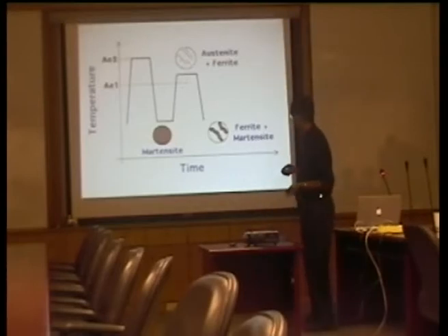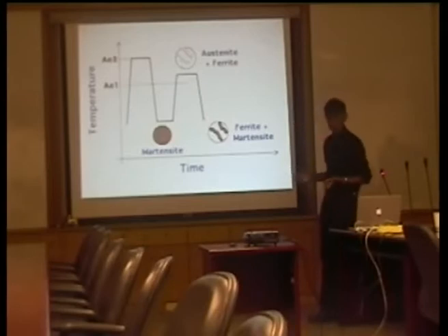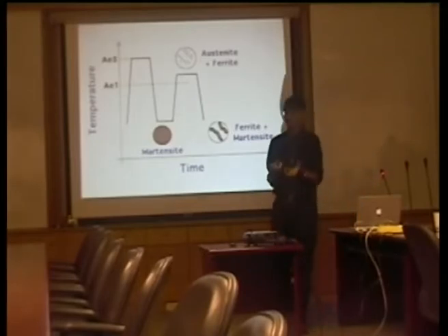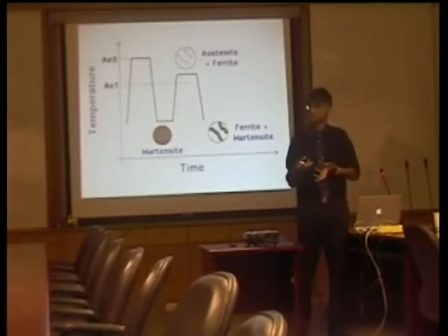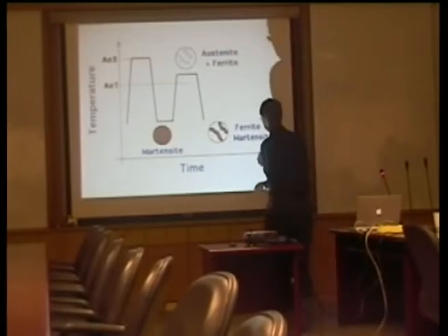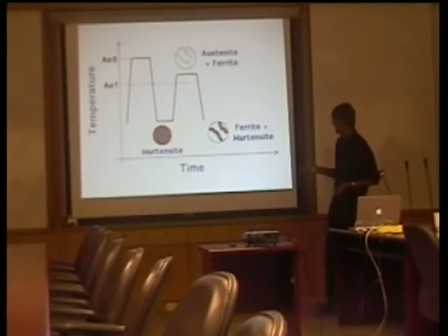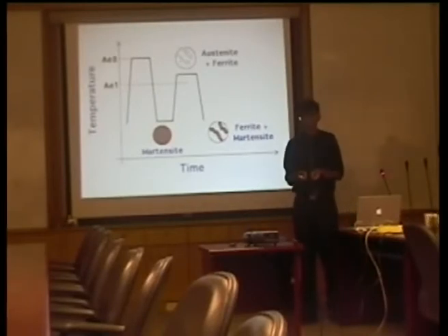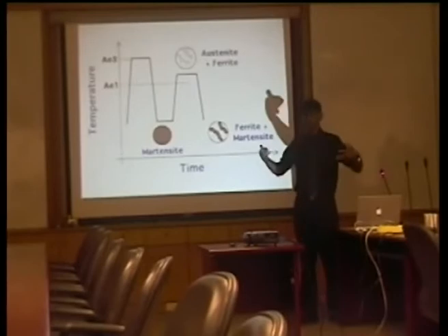And then you punch again, so you end up with a mixture of ferrite and martensite. So it's a dual-phase steel, the kind of steels that are going into cars because they are high strength. They're of the order of 700 megapascals in strength. So here you have ferrite, and here you have martensite, which is much higher in carbon. Yeah, because the ferrite has almost zero carbon in it. The martensite will have much more carbon because the carbon has gone into the austenite.